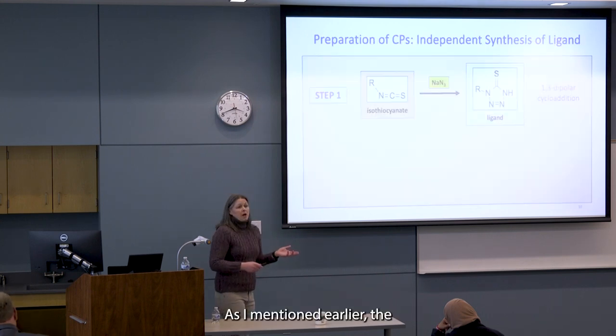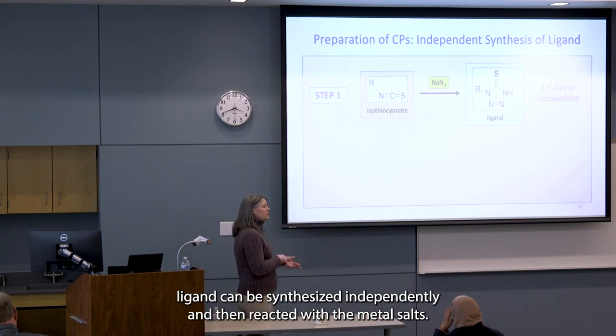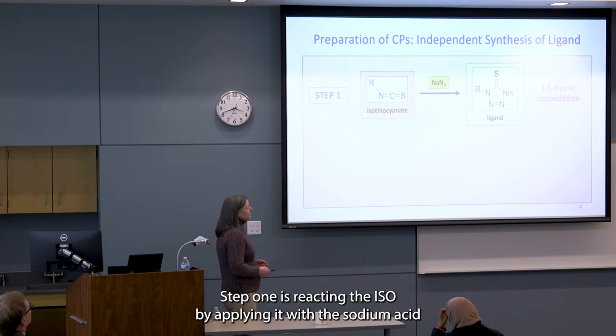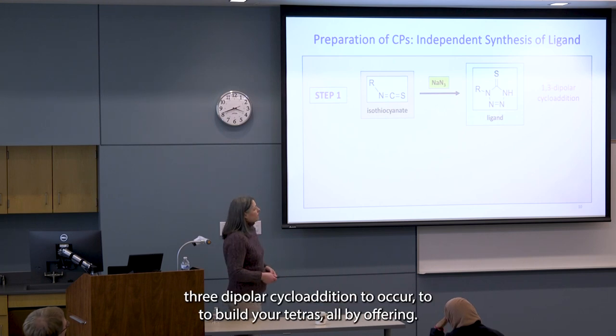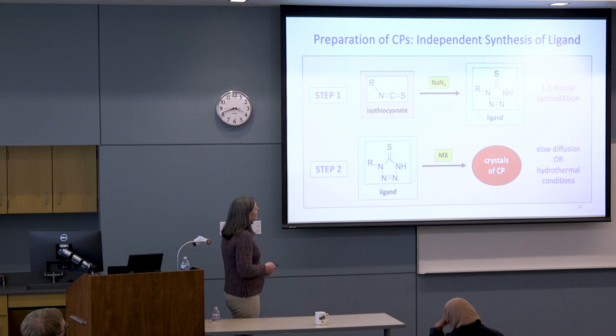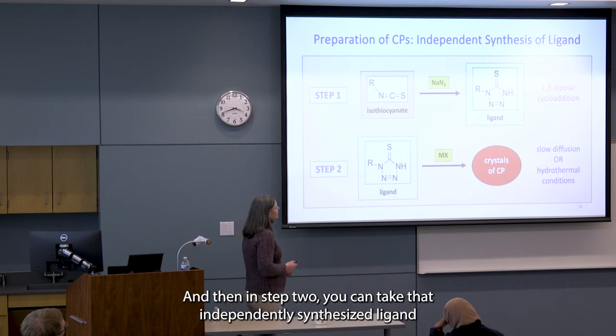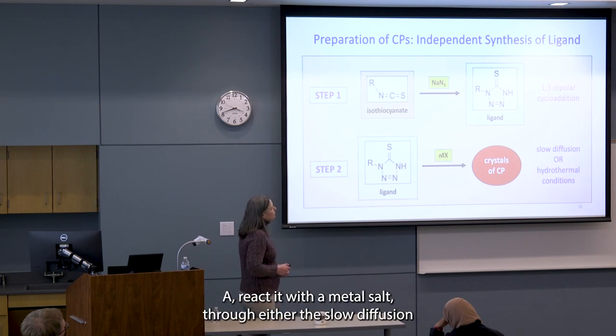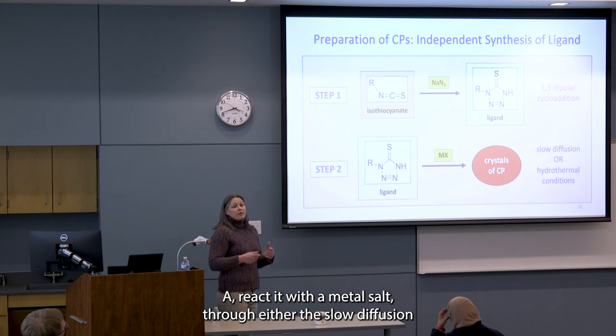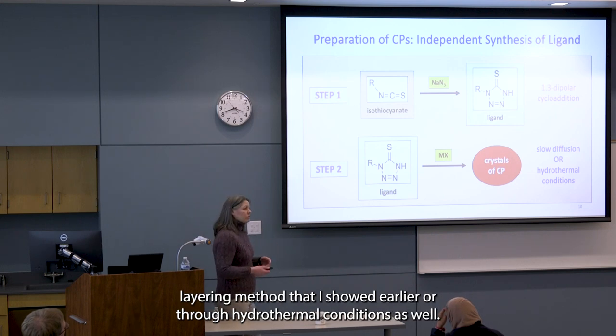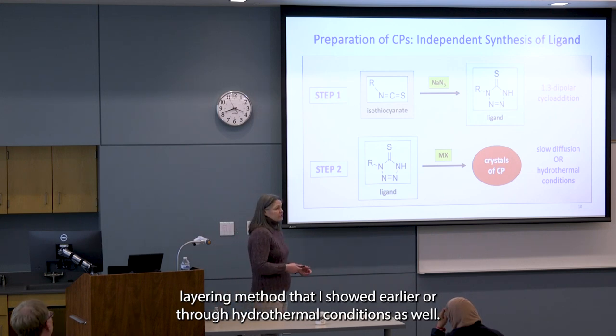As I mentioned earlier, the ligand can be synthesized independently and then reacted with the metal salt. So that's a two-step process. Step one is reacting the isothiocyanate with the sodium azide in order to get that 1,3-dipolar cycloaddition to occur to build your tetrazole thione ring. And then in step two, you can take that independently synthesized ligand and react it with a metal salt through either the slow diffusion layering method that I showed earlier or through hydrothermal conditions as well.